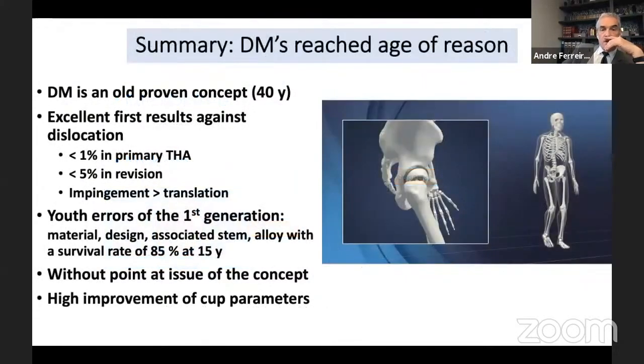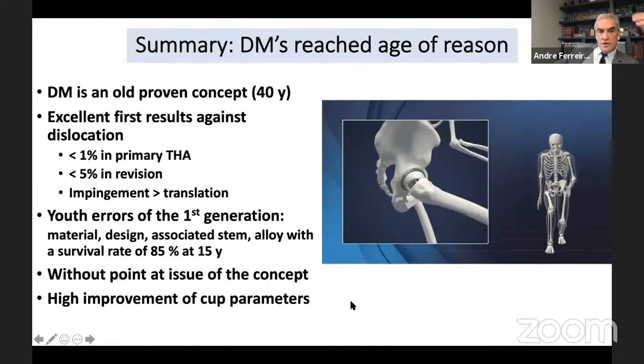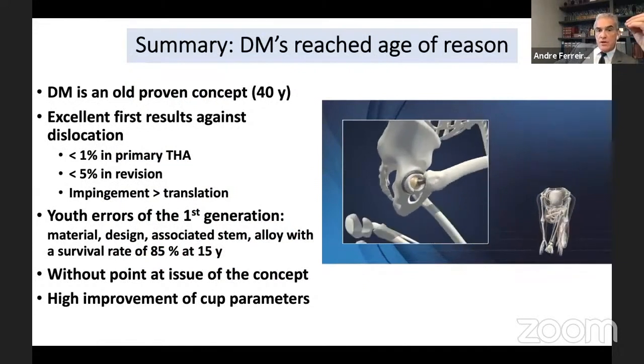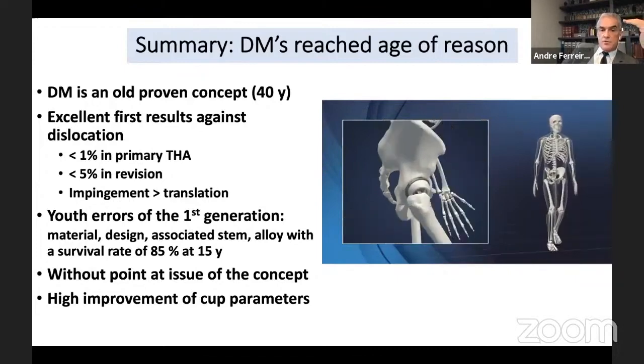So in summary, now we can say that dual mobility reached the age of reason. It's an old proven concept, more than 40 years, with excellent results against dislocation in primary and in revision. But most of the time, the results are better when the reason for dislocation is impingement. There were some errors of the first generation due to the material, sometimes of the design, but not of the concept. And of course, now there is a high improvement of the cup parameters.